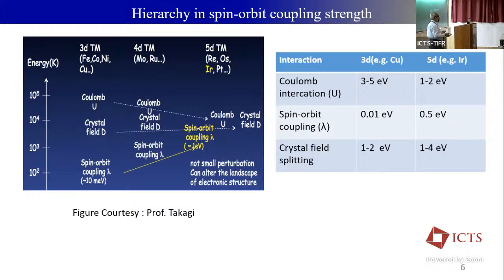So for the high-Z elements, the spin orbit interaction increases. Particularly for the 5d transition metal oxides like iridium and osmium, what happens is that in doing the physics of 3d, you can ignore the spin orbit interaction. It does not matter much. But when you come to the physics of 5d transition metal oxides, you cannot ignore the spin orbit interaction, because spin orbit interaction and Coulomb interaction kind of compete with each other. Because of this competition between the Coulomb U and the spin orbit interaction, you can see various kinds of novel phases that emerge in these spin orbit coupled materials, or iridates.